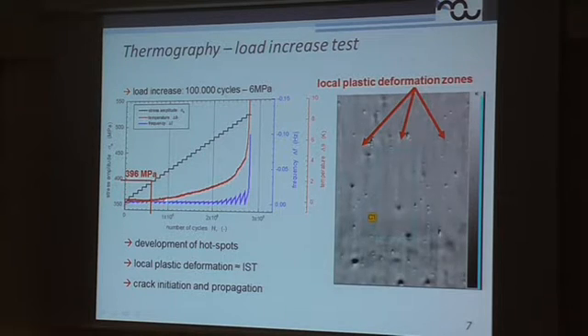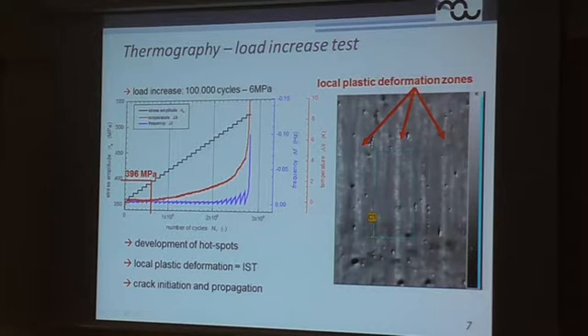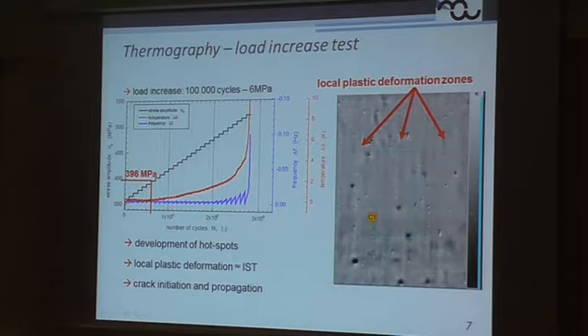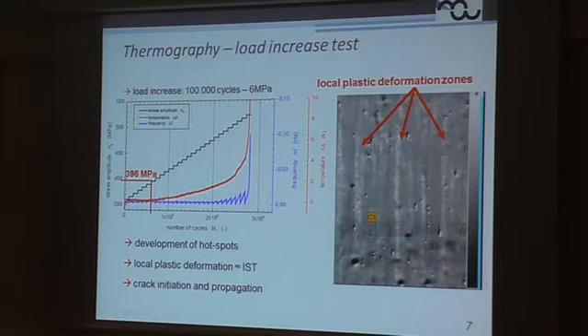So after 600,000 cycles, we see this lift-off of the temperature. And this lift-off can be correlated with the first start of so-called hotspots. So in the microstructure, we see the development of local plastic deformation, and the corresponding stress value here corresponds well with the cyclic yield strength that we have obtained by incremental step tests.